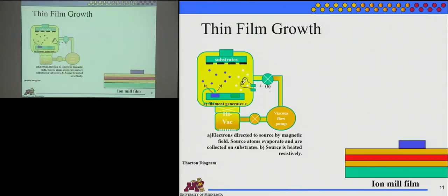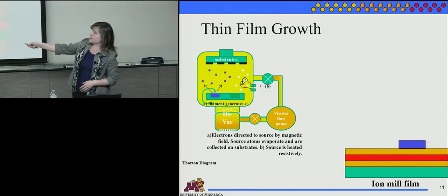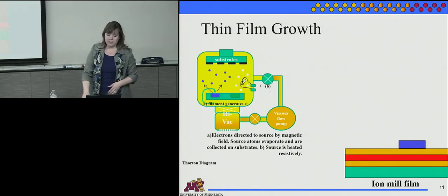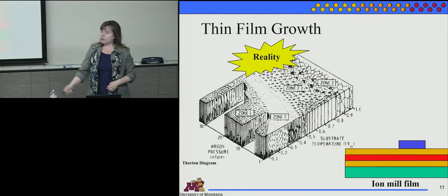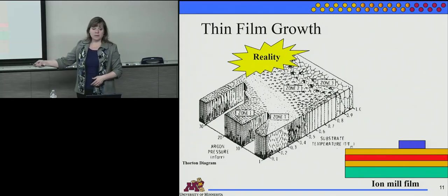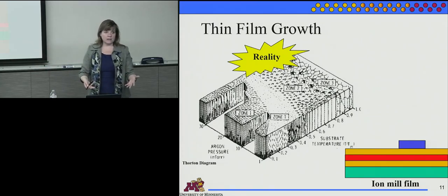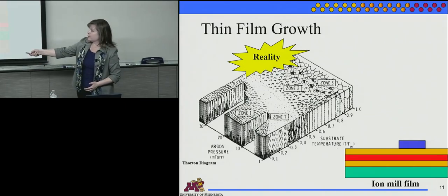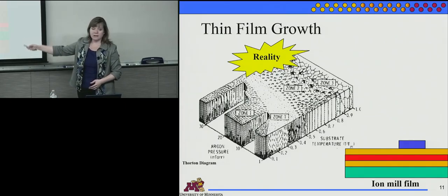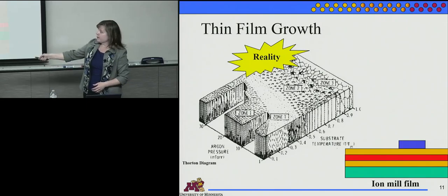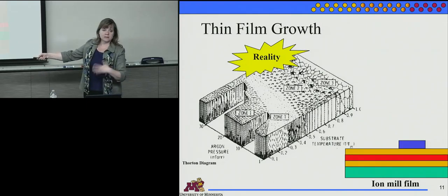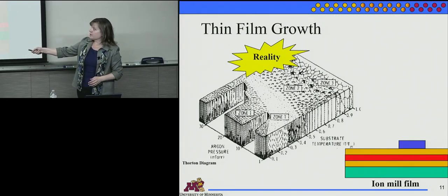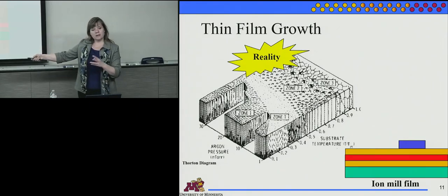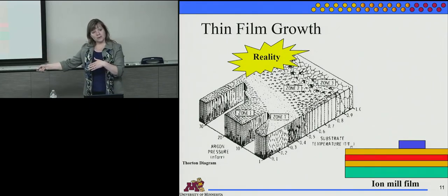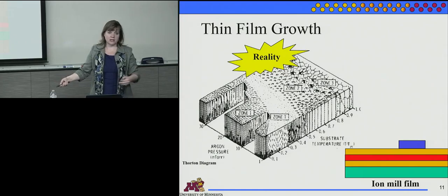What about thin film growth by itself? This is sort of representing evaporation, either thermal or E-beam, but sputtering as well. What you really get when you have vapor deposition is something that's called the Thornton diagram. So depending on what pressure you apply at and substrate temperature, you can get any one of these microstructures. But often they stay down in this, they don't heat the substrate for a lot of the growth, or as you pattern away, the smaller you want to make that bit, do you have a grain boundary or not in your device is going to change its properties.